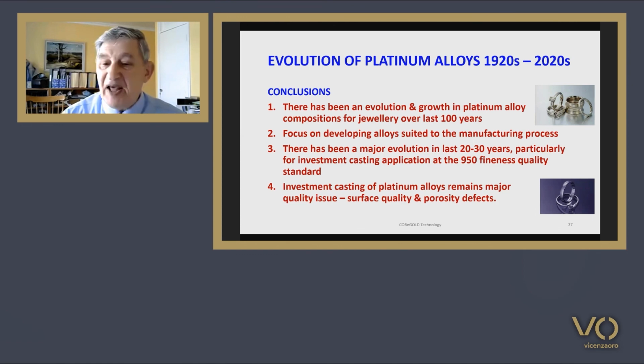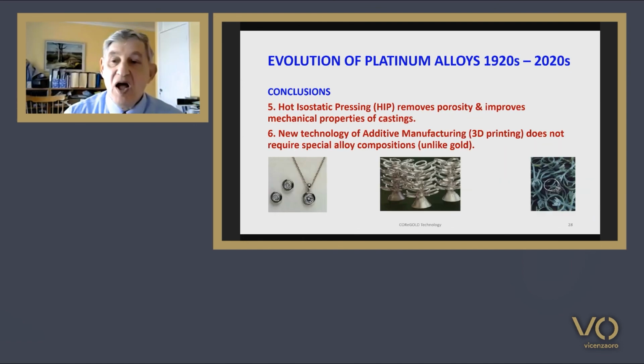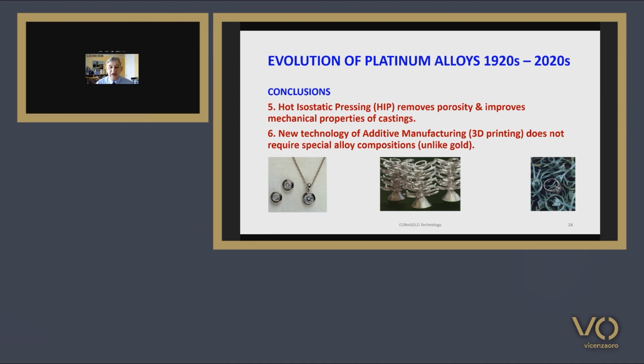Investment casting of platinum alloys remains a major quality issue, particularly surface quality and porosity defects. It has been clearly shown that hot isostatic pressing after casting does remove porosity and improves the mechanical properties of castings. And lastly, the new technology of additive manufacturing does not appear to require special alloy compositions, unlike gold.